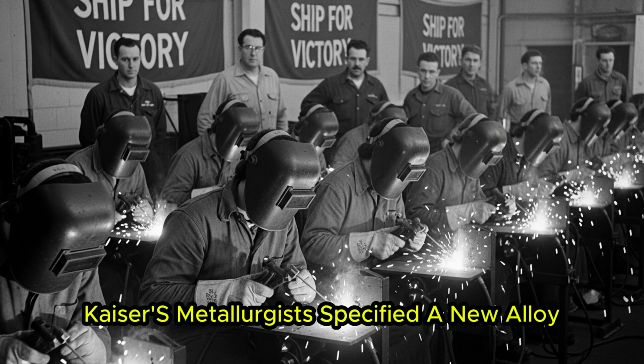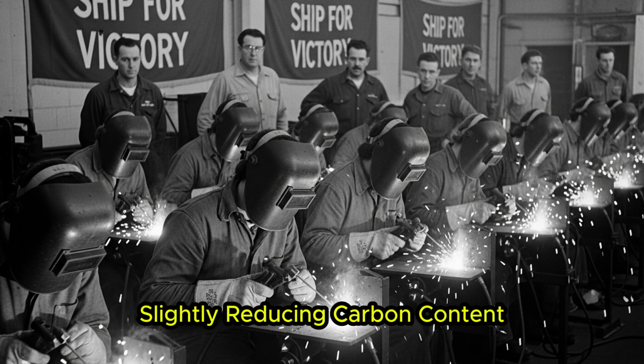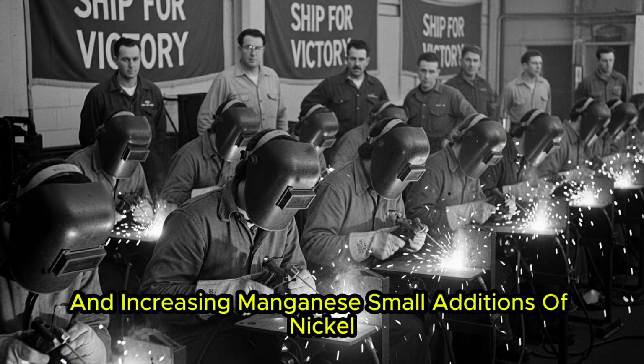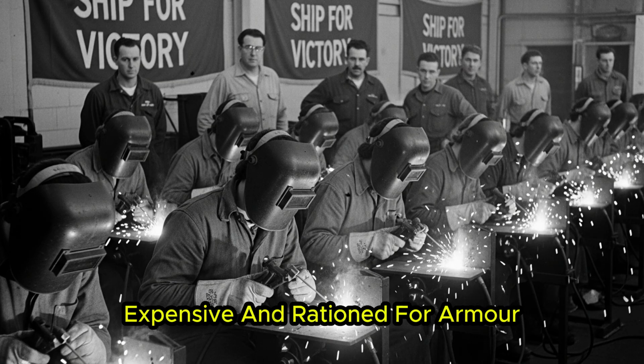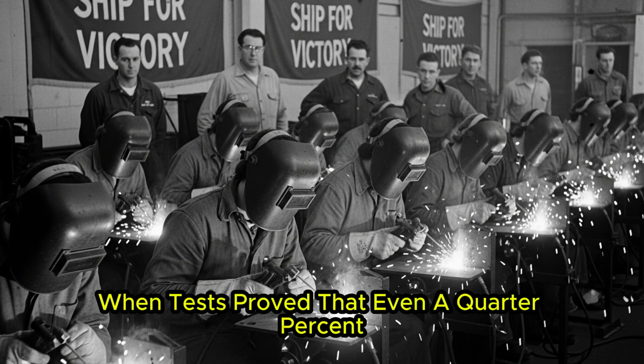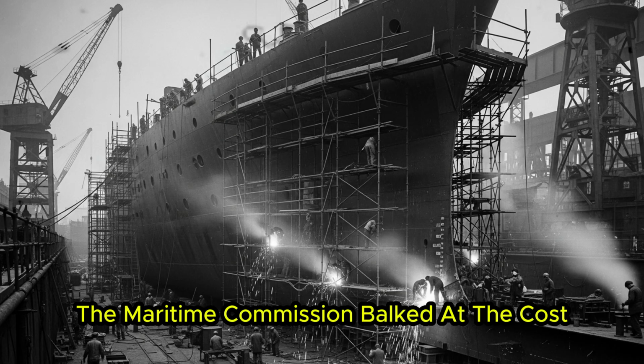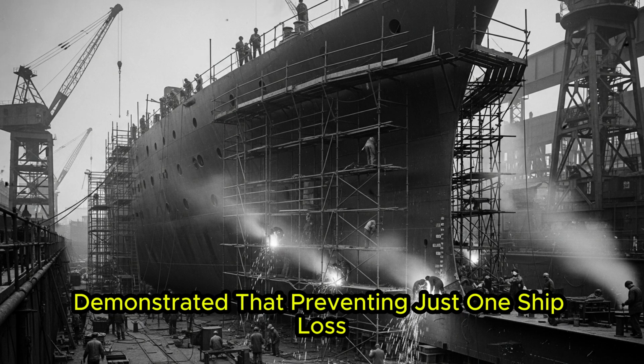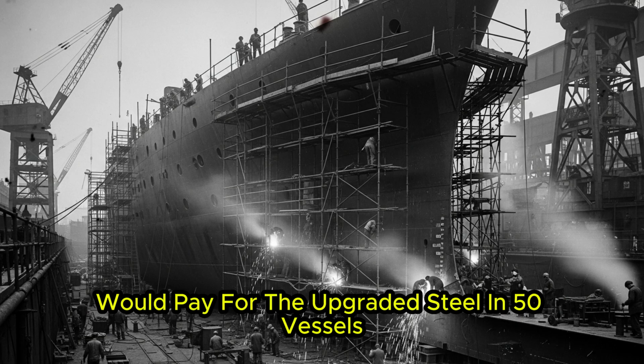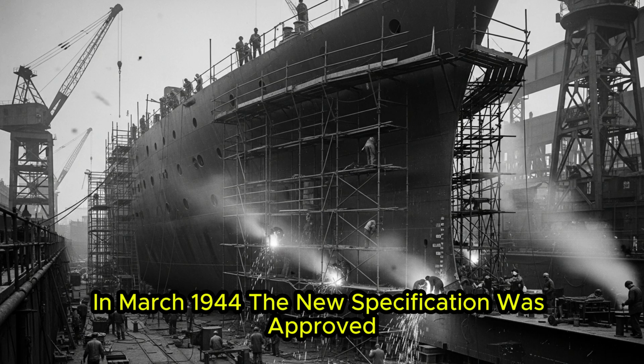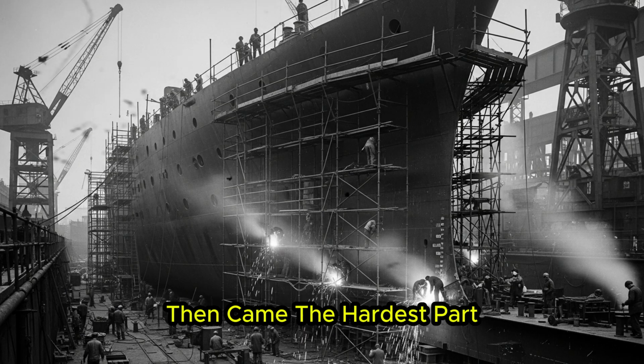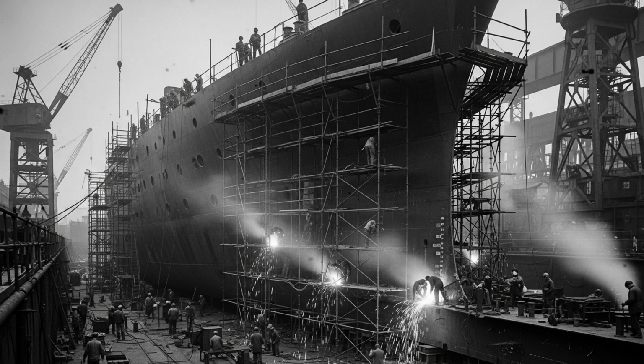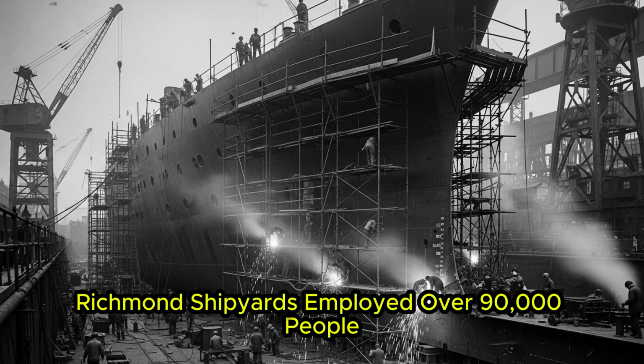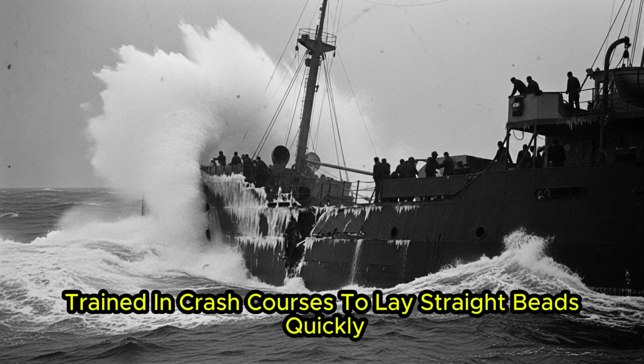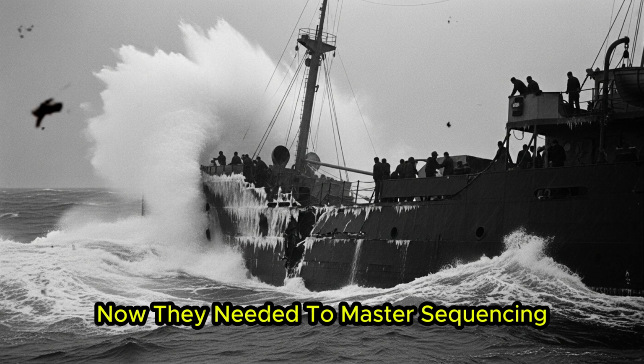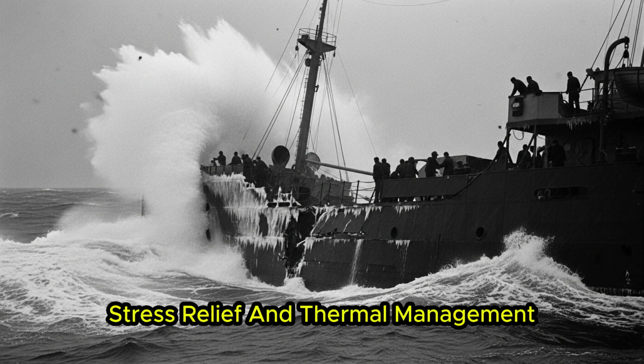Kaiser's metallurgists specified a new alloy with improved low-temperature toughness, slightly reducing carbon content and increasing manganese. Small additions of nickel, expensive and rationed for armor, were justified when tests proved that even 0.25% dramatically improved resistance to brittle fracture. The Maritime Commission balked at the cost until Kaiser demonstrated that preventing just one ship loss would pay for the upgraded steel in 50 vessels. In March 1944, the new specification was approved. Then came the hardest part, retraining an entire workforce. By early 1944, Richmond shipyards employed over 90,000 people, thousands of them welders trained in crash courses to lay straight beads quickly. Now they needed to master sequencing, stress relief, and thermal management.